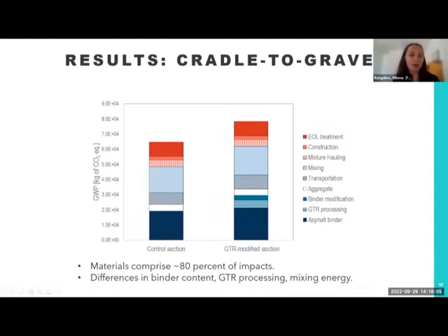Here we are breaking down the results for cradle-to-grave scope for these 2 sections, and we can see the difference between the 2. So first of all, we have asphalt binder. In GTR modified section, we have slightly higher binder content because GTR modified binder has increased viscosity, and it's used with open graded aggregate gradation, so we need a little more binder to achieve the same result. But that's not all. With the binder, we also have binder modification process as well as GTR processing. All of that comprises our modified binder.